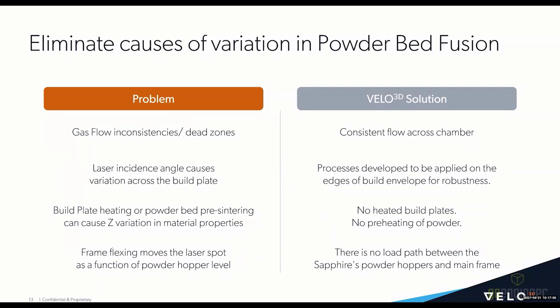And then another common problem is if you're working with heavier alloys such as Inconel 718, you can have frame flexing as a function of the powder hopper level. So when the machine is full of powder, the frame flexes down and the laser spot can move. And then if you refill the powder hopper, it moves again. So this makes it very challenging to characterize. However, if we look at the Velo3D Sapphire, there's no load path between the powder hoppers and the mainframe, and so it's not a stressed member. Because of that, we don't encounter this problem either.